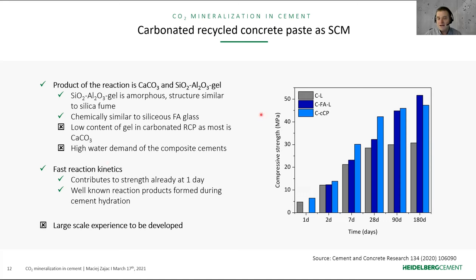And then on the right-hand side, I would like to show you the evolution of the compressive strength of the three composite cements, those tests we conducted in our laboratory. A reference LC cement, this is clinker blended with limestone at 40% replacement ratio. A typical pozzolanic cement, so clinker blended with fly ash and limestone at the same replacement ratio. And then our new composite cements, here CC, this is a carbonated cement paste. All those three cements are characterized by the same replacement ratio of the clinker by the supplementary cementitious materials.